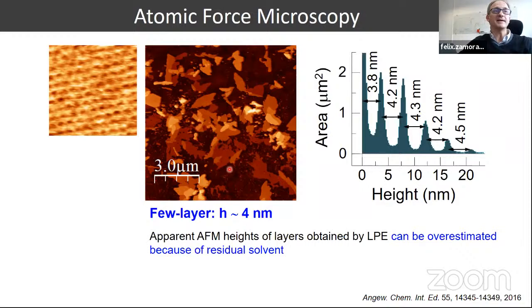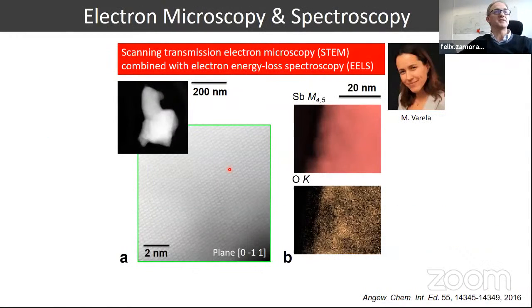That was also confirmed using advanced microscopy and spectroscopy techniques in collaboration with Maria Varela. Here I showed you the STEM results with the atomic resolution and the EELS experiment, in which we confirm the composition of our material, which is based, of course, on antimony, showing a certain amount of oxygen probably coming from the solvent or partial oxidation of the material.